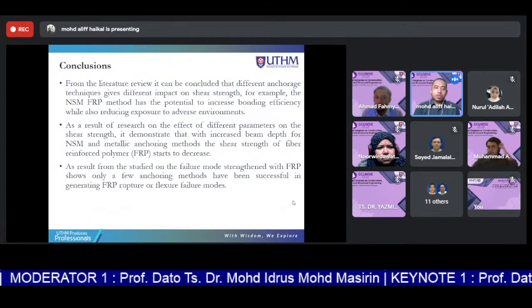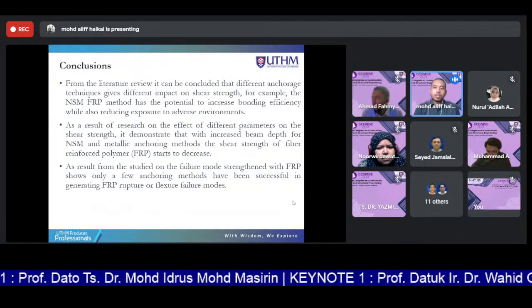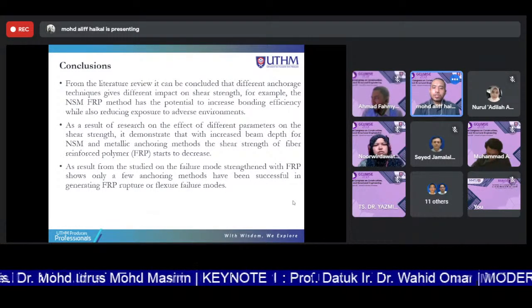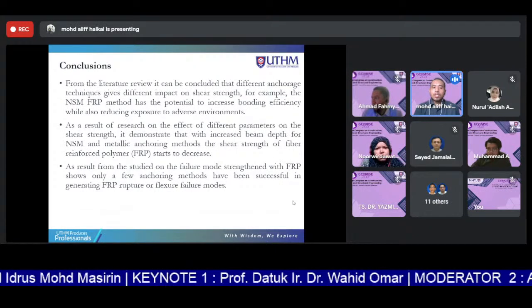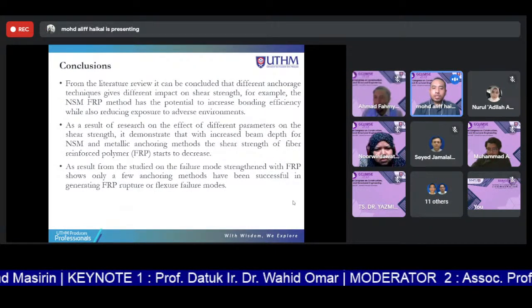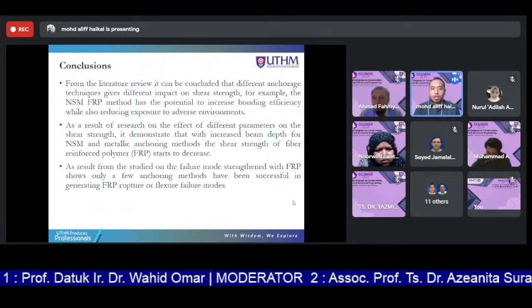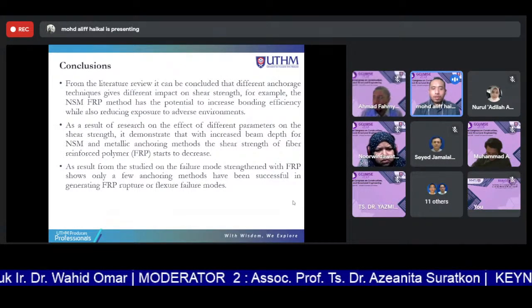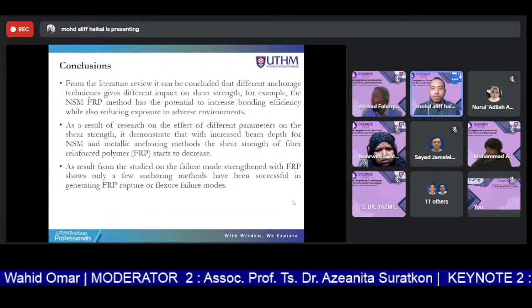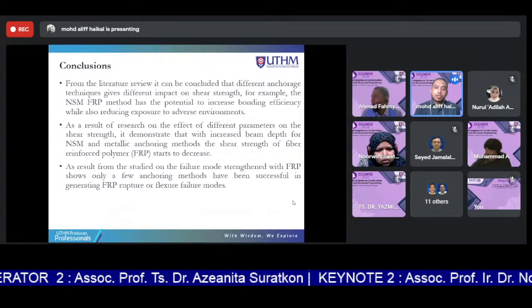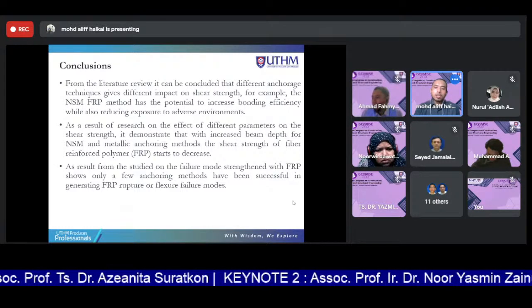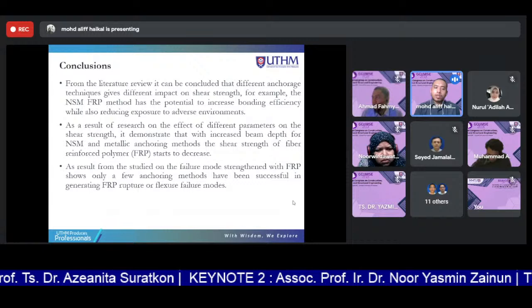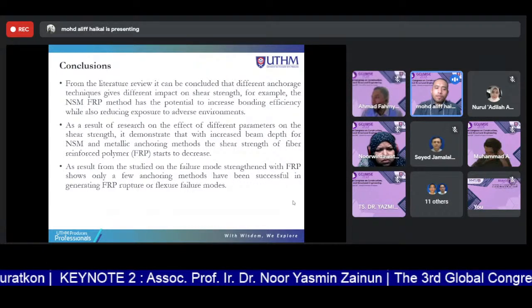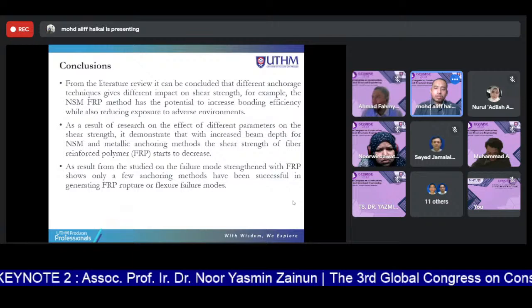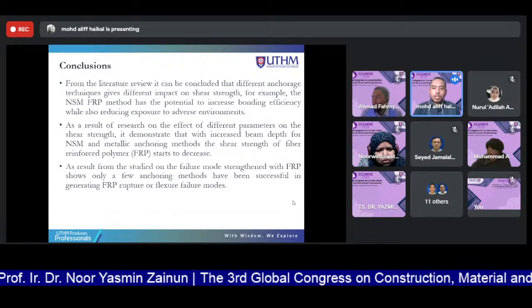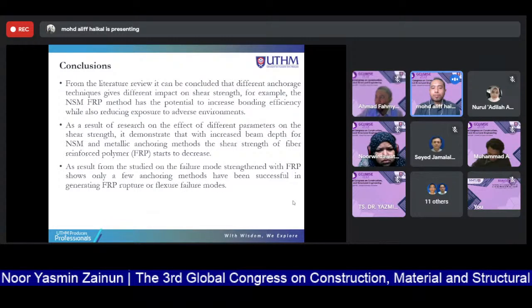Okay, for the conclusion, from the literature review, it can be concluded that different anchorage techniques give different impacts on the shear strength. For example, the NSM FRP method has the potential to increase bonding efficiency, but also reduce exposure to adverse environment. As a result of research on the effect of different parameters on the shear strength, it demonstrates that with increased beam depth for the NSM anchorage method, the shear strength of fiber reinforced polymer, FRP, starts to decrease. As a result from the study on the failure mode, strengthening with FRP shows only a few anchorage methods have been successful in generating FRP rupture or flexure failure mode.